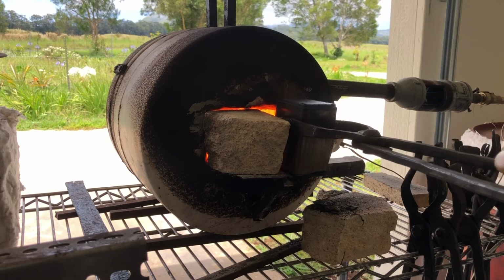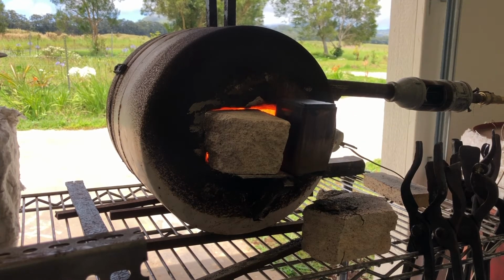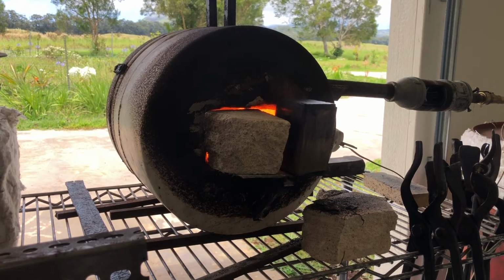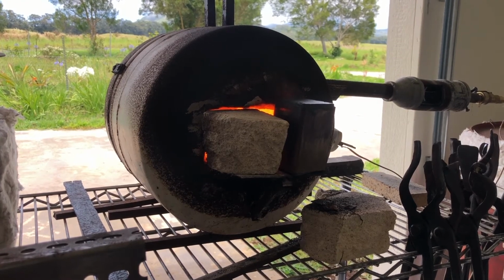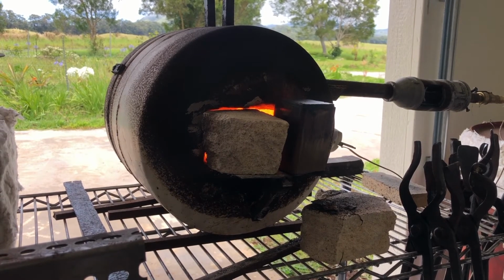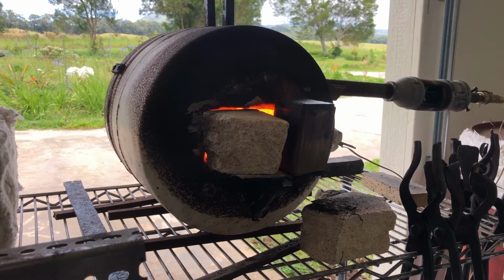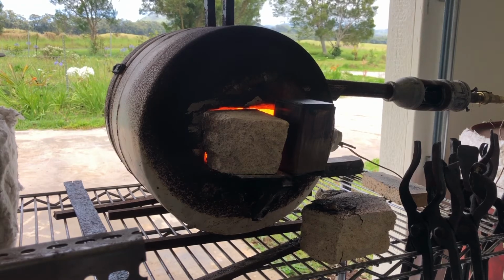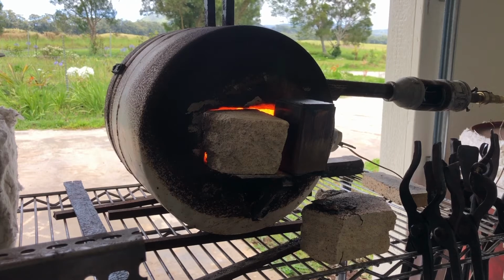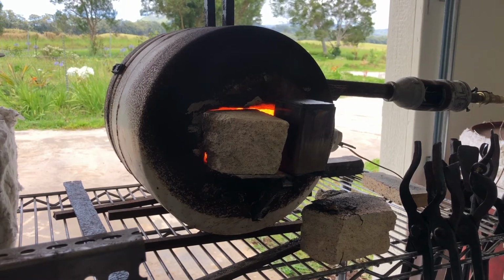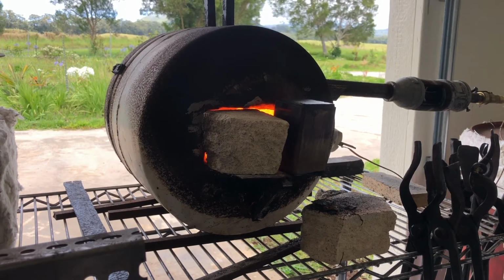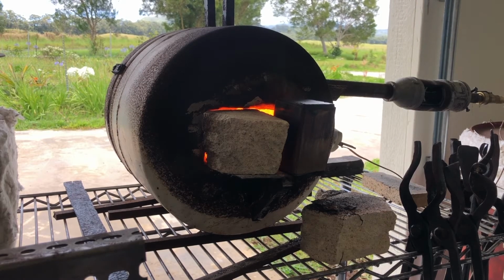So the canister has been baking at 550 for about an hour. And as you'll recall, I had already baked the clay block itself up to 450. So pretty quickly here we should start to get some fume out the top of the can, and that'll be the methyl cellulose burning off. Since I've already baked it as hot as I have, there's not going to be nearly as much. So might not get too much, but it is a good idea to always preheat in front of the forge like this. If you do still have stuff in there that needs to burn out, you really don't want it shooting powder all over the inside of your forge.